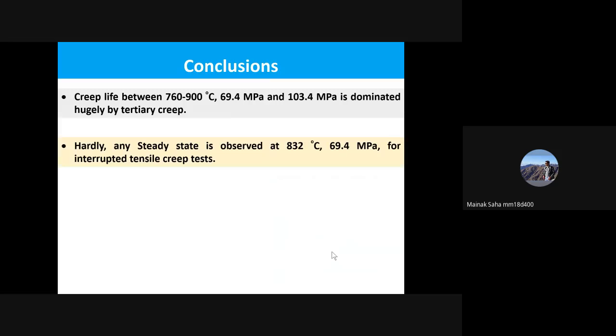Then secondly, earlier the claim was that there is a steady state creep observed at 832 degrees for 69.4 MPa for interrupted tensile tests, but definitely we do not see it. So based on the activation energy and the stress exponents, we can definitely say that there is no steady state observed at that particular temperature and stress level, even for the interrupted tensile creep tests.